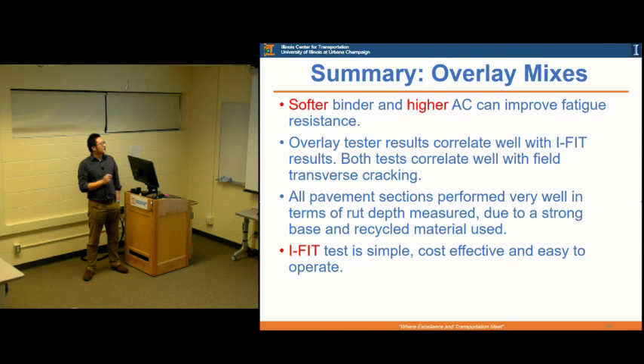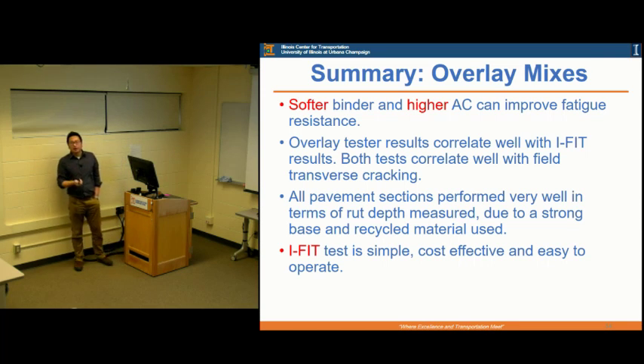So that's the correlation between the test parameters and the field performance. Some findings here: if you have a soft binder, meaning you're using a lower PG, and you get a little bit higher asphalt content, you can improve your mix's fatigue resistance. We also see that the overlay tester results had a good correlation with iFit, and both of them correlate with the field transfer cracking.